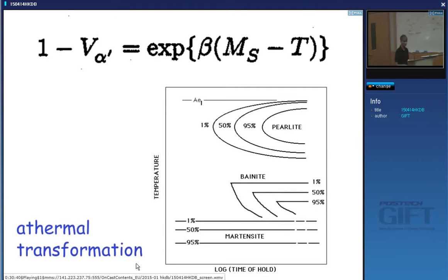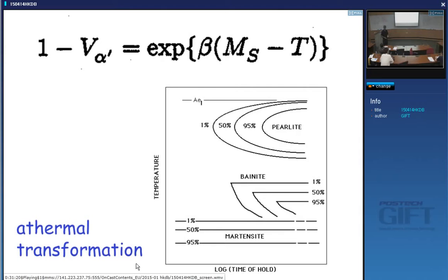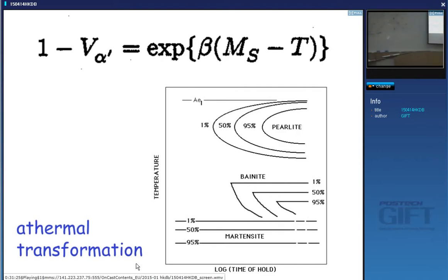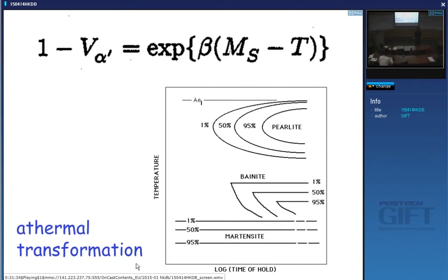The transformation is athermal — what does athermal mean? If I'm forming pearlite and hold austenite at a fixed temperature, I see transformation progressing as a function of time from 1% toward 100%. That isn't the case with martensite. If I cool to a certain temperature, I get only 1%; I have to cool further to get 50%. The equation expresses volume fraction of martensite as a function of undercooling below MS — there's no time term. Very little thermal activation is needed to form martensite. This observation is only true when martensite forms rapidly — so rapidly we can't monitor volume fraction evolution.